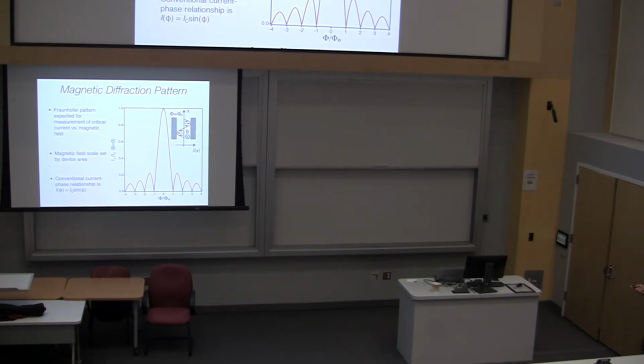Remember, the critical current or the supercurrent looks like I_C sine phi. So if I allow phi to evolve by 2 pi, I should basically go through my whole sinusoidal curve of the current phase relationship as I go along the width of this junction. And since sine has an average of 0 over one period, if I put one flux quantum such that the phase has to evolve by 2 pi across this junction, I basically trace out my current phase relationship. Since the average is 0, when one flux quantum is going through the device, you have half a supercurrent going this way, the other half going this way, and it gives you a 0 overall in the supercurrent.